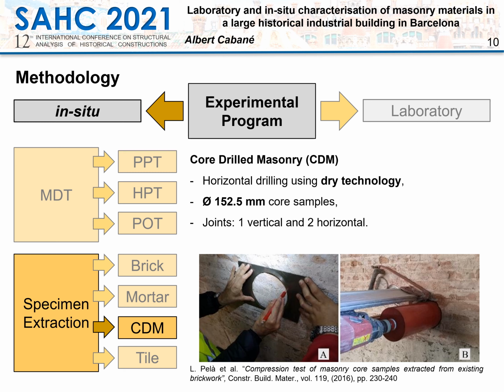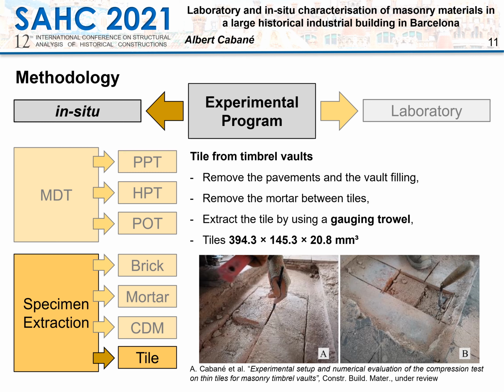The extractions of the core drilled masonry samples were done by horizontal drilling using the dry technology proposed by the previous research developed at UPC. It is important to mark the samples before the extraction to guarantee the correct drilling. At least 3 extractions are necessary for the correct characterization of the masonry, although in this campaign, where it was possible, up to 5 samples were collected. Once the samples have been extracted, it is necessary to maintain the integrity of the cylinders, avoiding disintegration of the sample components. Finally, in this campaign, timbrel vault components were characterized too.